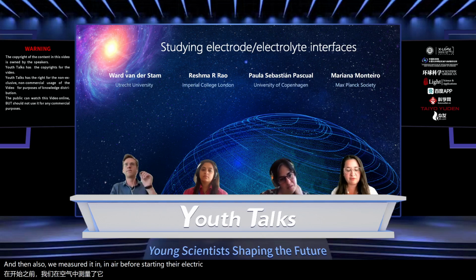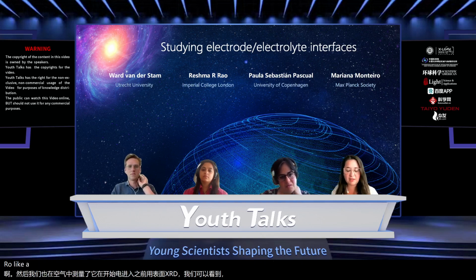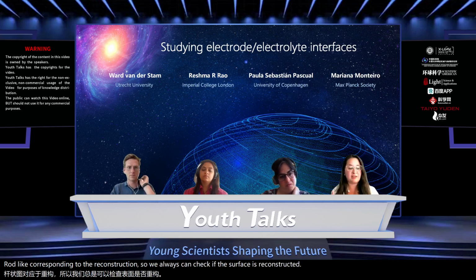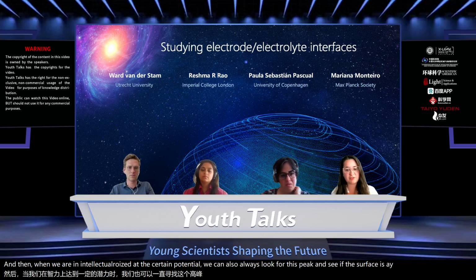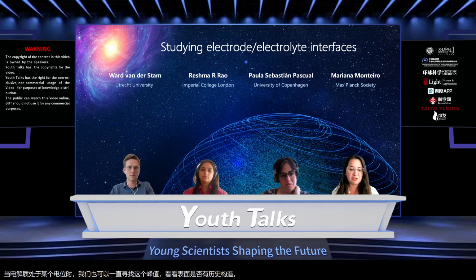And then also we measured it in air before starting the electrochemistry with surface XRD. We can see a rod corresponding to the reconstruction, so we always can check if the surface is reconstructed. And then when we are in electrolyte at a certain potential, we can also always look for this peak and see if the surface is still reconstructed. Then we measure, and then you know that you are always measuring on the hexagonally reconstructed